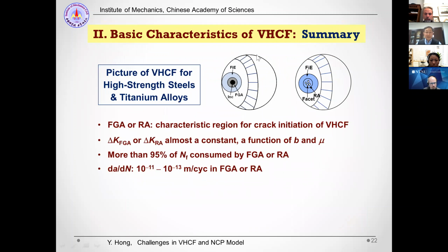Okay, now as a summary of this part, I would like to show this picture of crack initiation and early growth for high strength steel and titanium alloy. We say that the initiation region of FGA is a characteristic region for crack initiation, and the value of delta K_FGA or delta K_RA is almost constant and is a function of Burgers vector and shear modulus. More than 95% of total fatigue life is consumed in the initiation region, and the crack extension rate is very low, between 10^-11 and 10^-13 meter per cycle.